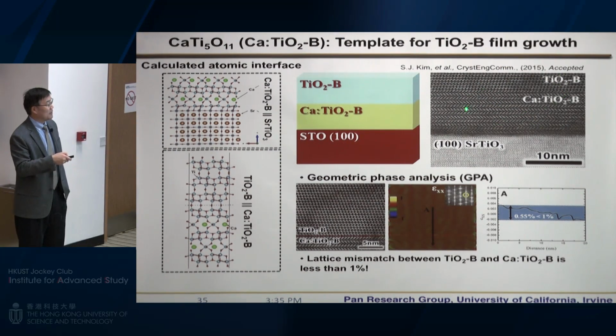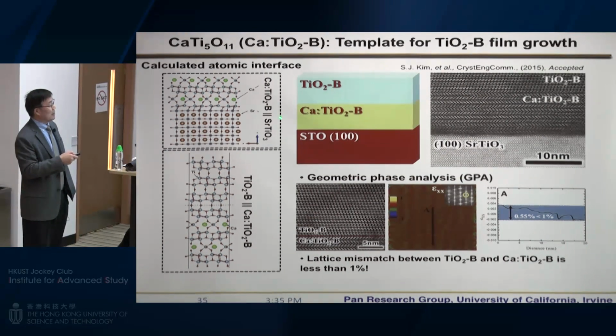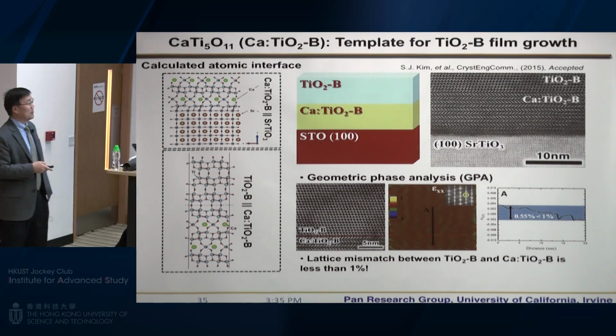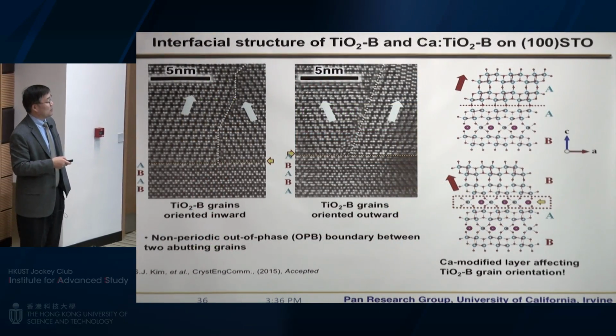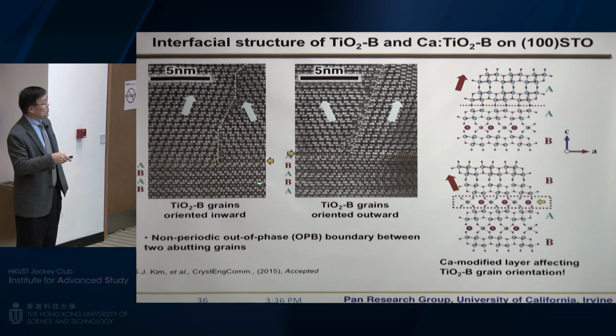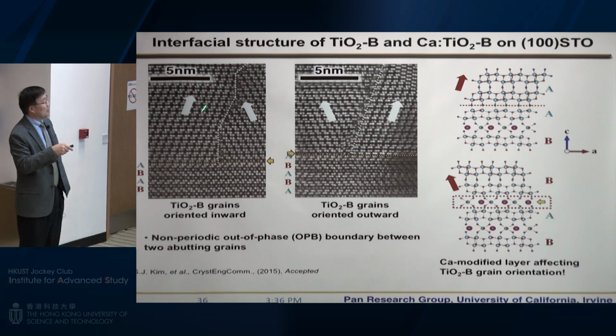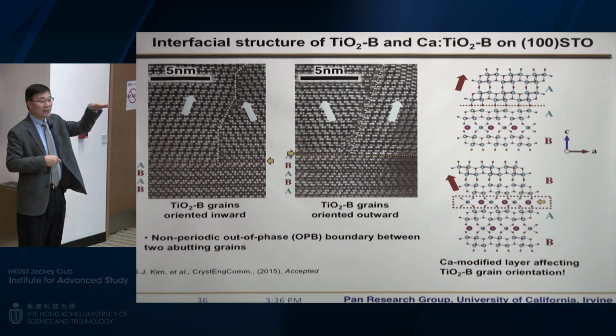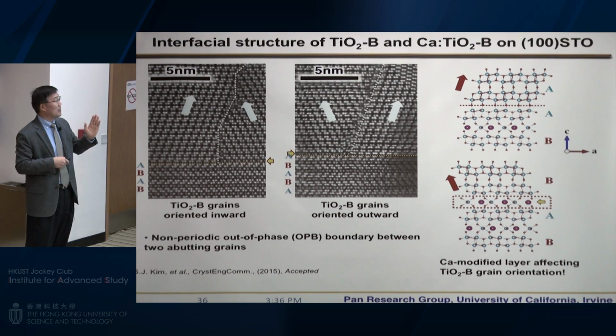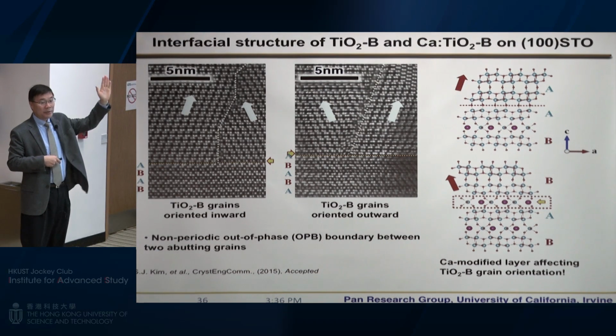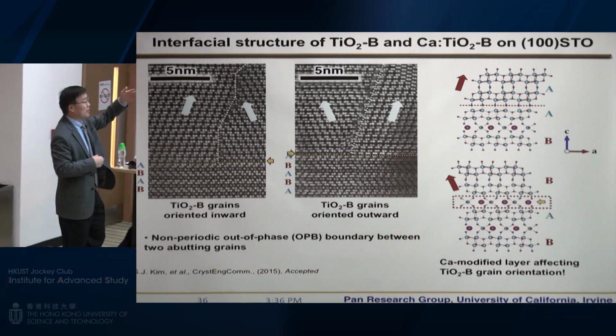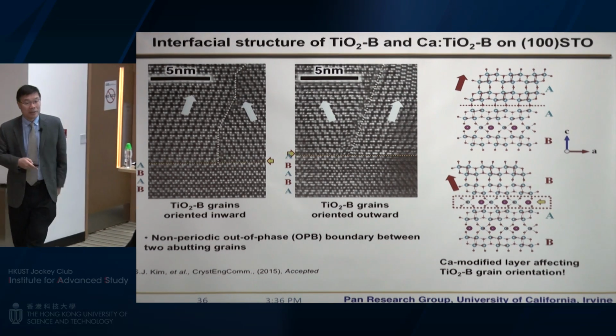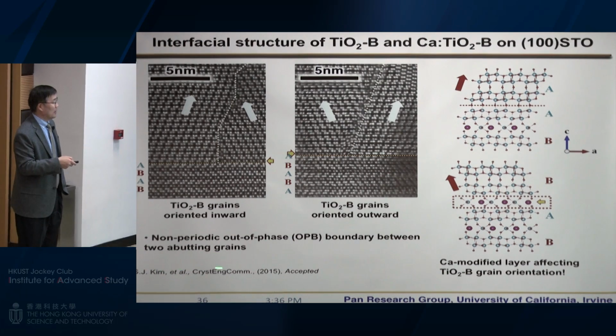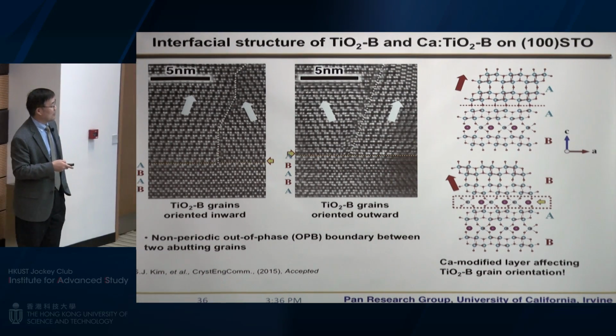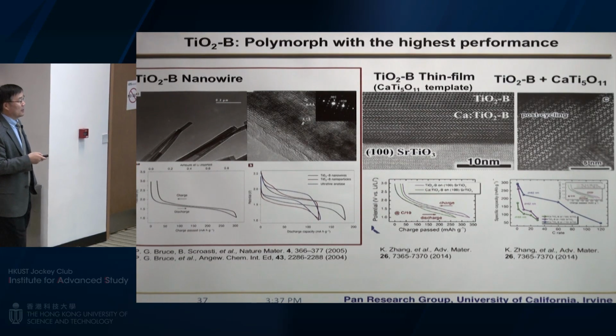It became very good, very successful. So then we made a very nice bronze phase of TiO2. I can even make a calcium-doped TiO2 bronze structure, so we have two different kinds of model structure. By changing the substrate orientation, we can also grow bronze B with different orientations. That means the diffusion channel can be parallel to the film or perpendicular to the film. Then we did thin film battery testing, and you have different channels of diffusion. This was the work of Kui Zhang, and he published on bronze material. He also just graduated last year.